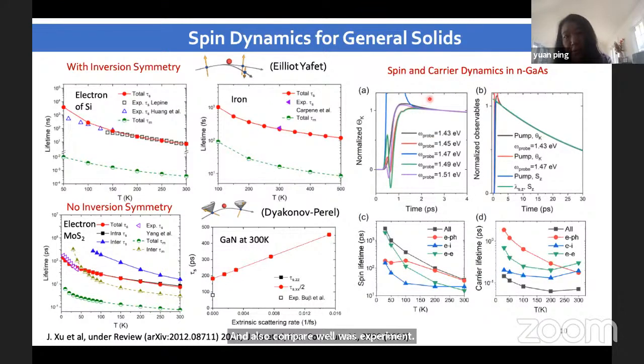And more importantly, we show an example of gallium arsenide spin and carrier dynamics initialized by a circularly polarized pump, and we probe the system. You can look at a shorter time range, which is mostly carrier relaxation with fast oscillation. In the long time range, you can see an exponential decay, from which you can extract the spin lifetime. There we show the Kerr rotation angle and the spin expectation value basically overlapped, which gives you the same value as expected by the Kerr